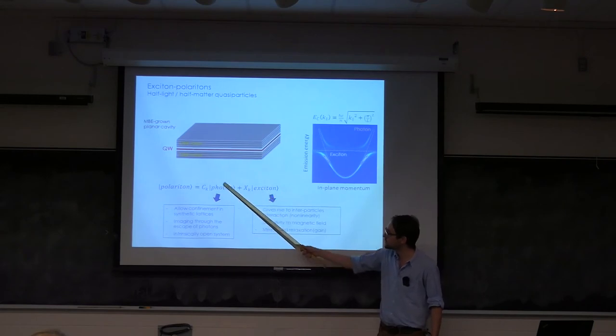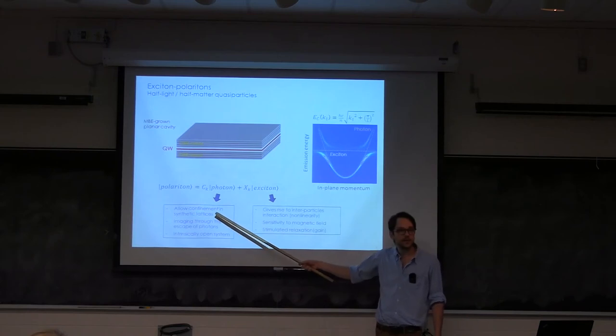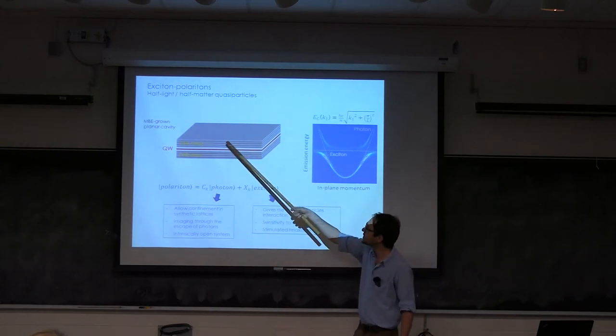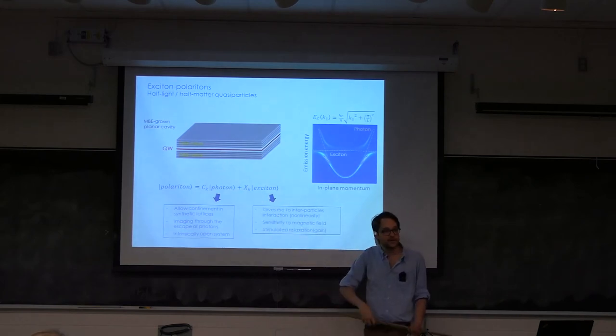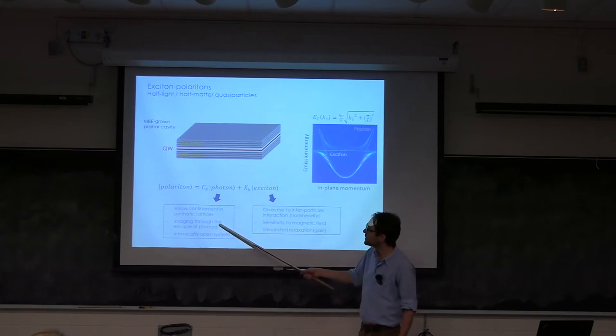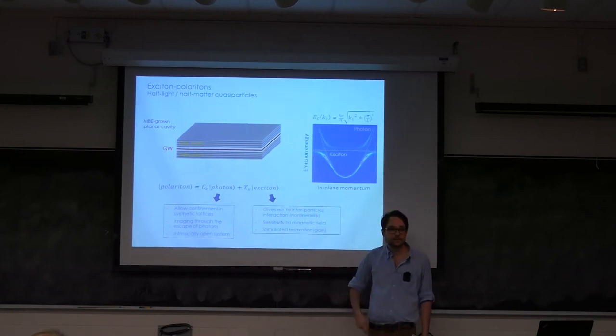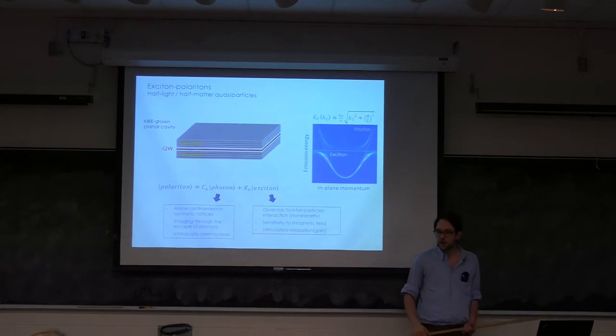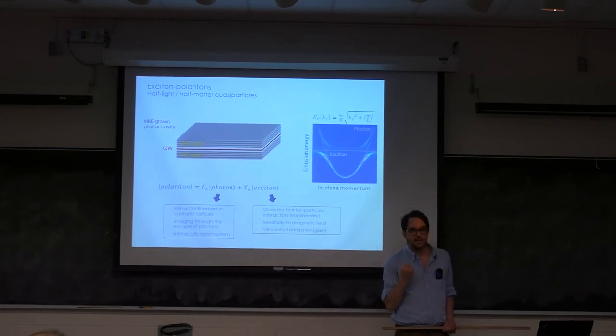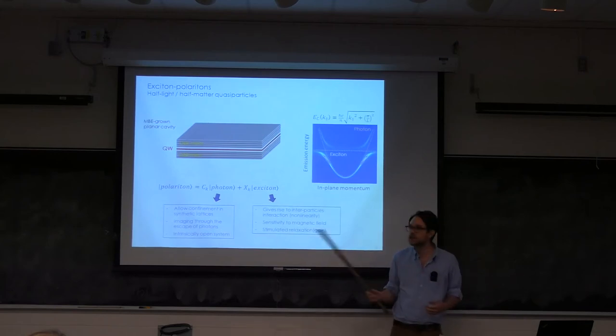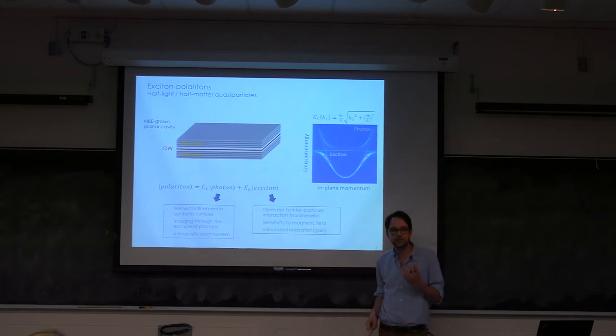All right, so these particles are interesting for both of these constituents, from their photonic fractions. This allows us to confine them in synthetic lattices. So I will show you how we can etch, in fact, these planar cavities to form arrays that confine these polaritons in a really well-defined geometry. Also, these are really dissipative because photons will eventually leak outside, typically on a timescale around 50 picoseconds. So we can just take these photons and send them to our apparatus. And since these photons carry with them all the properties of the polaritons, their energy, their momentum, their phase, we can really do basic spectroscopy techniques to reconstruct all the properties of the polaritons.